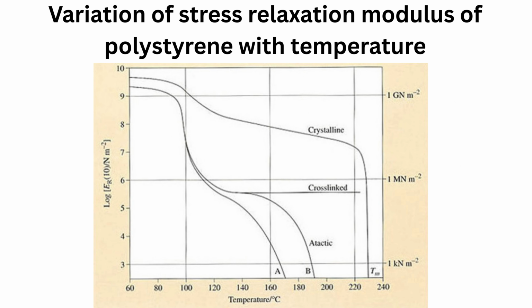Effects of structure on viscoelasticity. If a single measurement of ER is taken at an arbitrary but fixed interval of time, say 10 seconds, then it will vary with temperature in a way rather similar to the viscoelastic master curve. The effect of lightly cross-linking the material is to eliminate flow of any kind, extending the region of elastomeric behavior to higher temperatures. Heavier cross-linking will move the rubbery plateau upwards, and the same net effect is achieved by crystallization.